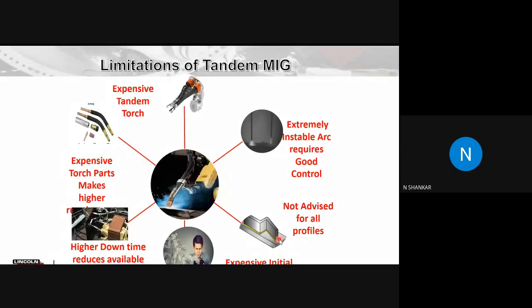You can do it on a different level, but you cannot have sharp bends or sharp corners where your tandem torch will not be able to reach. You cannot do it on smaller diameter pipes where the material will tend to flow over. And also it is going to be very expensive, because you're going to use two power sources, two wire feeders, all with a special torch and a special controller. So it's not going to be twice that of a single wire system. It is much more than that. So that is why there are a lot of limitations that come with tandem MIG.